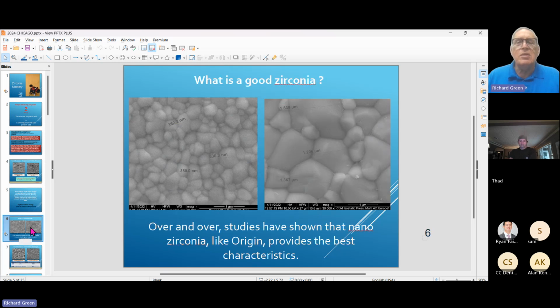And this shows you again that on the right, it's cold isostatic pressed. It's A2 from a European manufacturer that we all know. And this is our material on the left. So when you see how big these particles are, you know now why they do not respond well to rapid sintering. They don't transmit heat easily. They retain voids, as you can see here in the particles. When you cold isostatically press zirconium, you have to use a binder. There's got to be a glue in there to hold the material together. And so when they pre-sinter up to the 1,000 degrees like we do with our zirconia, that binder burns out. And that's great, but it leaves behind voids because it took up space. And those voids tend to resist further compaction.